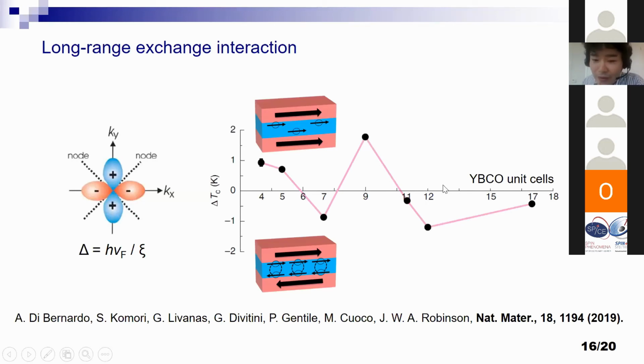And this is actually an unconventional effect because if we use S-wave superconductor, for example, niobium, we cannot observe TC switching if niobium becomes thicker than its coherence length. And this is more than 50 times thicker than the coherence length of YBCO. So this exchange interaction is unconventionally long range. And we are thinking it is related to the D-wave pairing symmetry of cuprate superconductors.